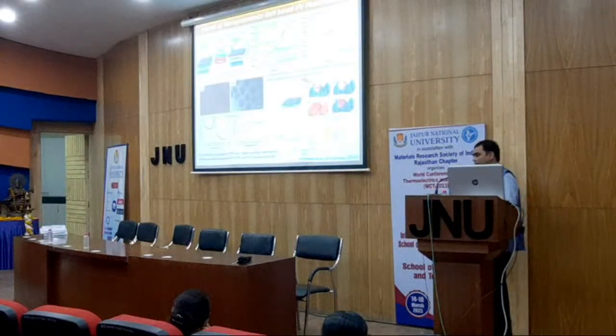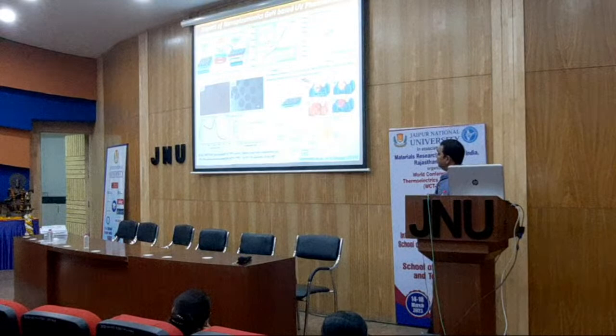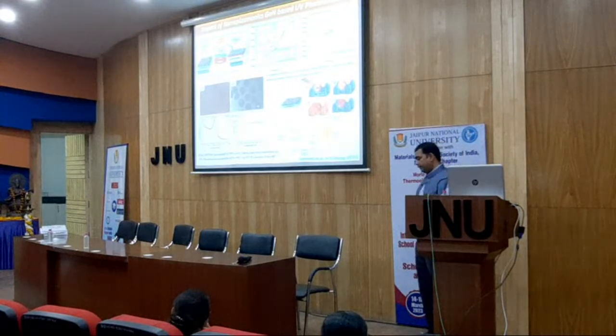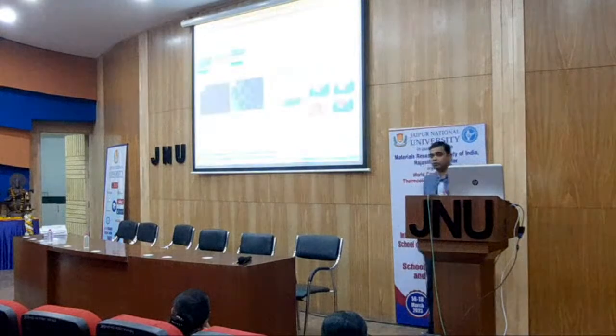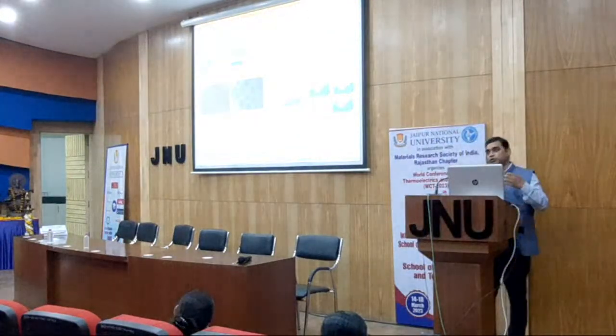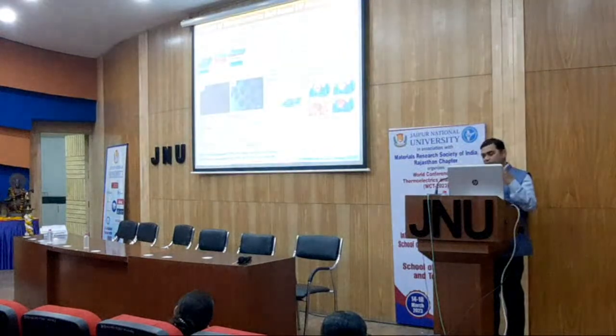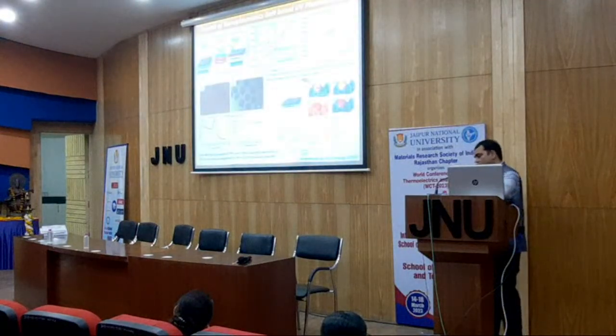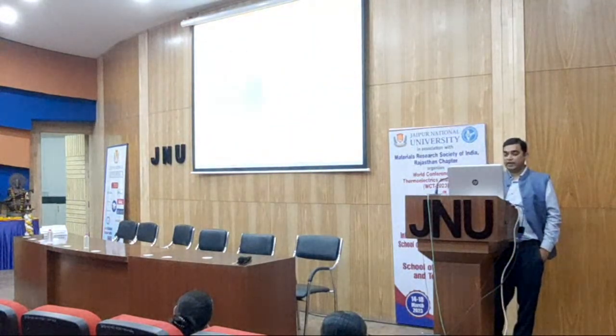Now, as we know, a lot of research is going on in different materials where metal nanoparticles are being used to interact with the optical light, generating localized surface plasmons. So we have also utilized gold nanoparticles to analyze the impact of these plasmonic structures on the grown gallium nitride films. And one can observe that the gallium nitride nanoisland is showing an enhancement in photocurrent by 10 times.